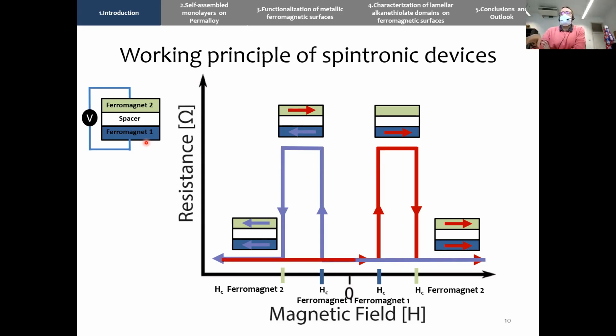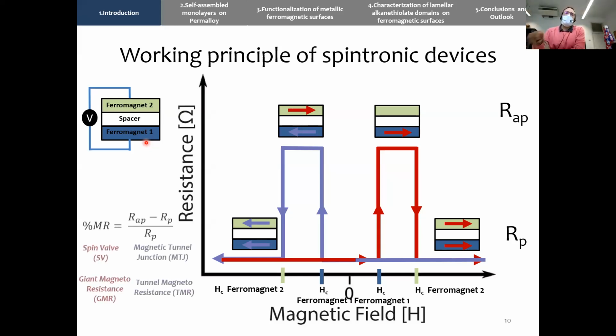So we can define, and then if we cycle back, this cycle can be repeated several times. So with this, we can define two situations of resistance, taking into account that the lowest resistance is the resistance in the parallel, and the highest resistance is the anti-parallel configuration. And we can also define the magnetoresistance, the percentage variation, as the relationship using these two resistances.